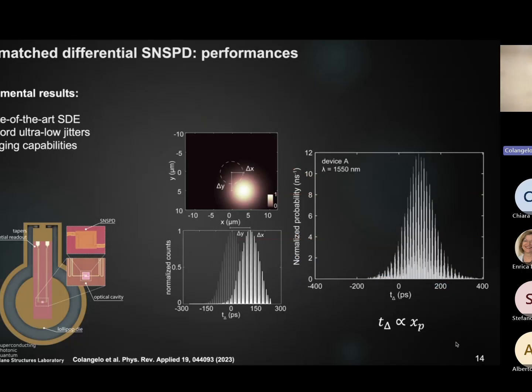Now, this detector, thanks to the design, also has imaging capabilities, which is a little bit long to explain, but basically the core is that we are able to understand if the mode that we couple onto the active area of the device is misaligned from the center. And we do that by analyzing the output distribution of the pulse histograms. As you can see here, for example, this distribution is misaligned from the center, which is an indication that there is a delta Y misalignment through some processing.